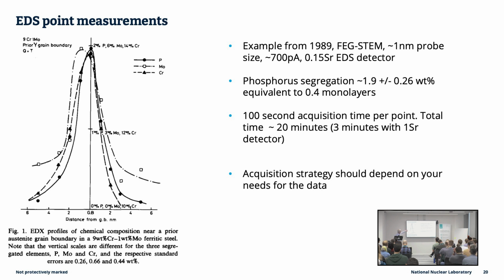And the result of that is that we can see there's very good, very smooth analysis of the compositional profile at the grain boundary, which is able to be quantified to show how much phosphorus was there in terms of phosphorus coverage of a single plane of atoms at the grain boundary. And if you're after that kind of measurement, you've really got to spend the time acquiring the data. Mapping will show you what's there, but you will not measure things unless you've got enough counts present.